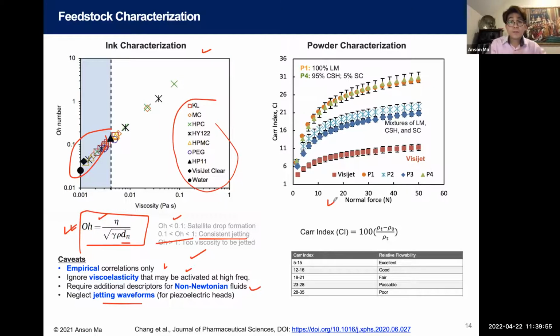And then you can also do powder characterization. This is work that, typically in the pharmaceutical industry, they handle a lot of powder. What you see here, VisiJet, is a commercial powder. It's calcium sulfate hemihydrate, or gypsum, that they use for binder jet printing in non-pharmaceutical applications. Then you can measure, for example, the density of your powder, both the bulk density and also the tap density, meaning that you apply normal force and measure the density. From there, you can calculate an index called the Carr index. The lower the index, the better the flowability.